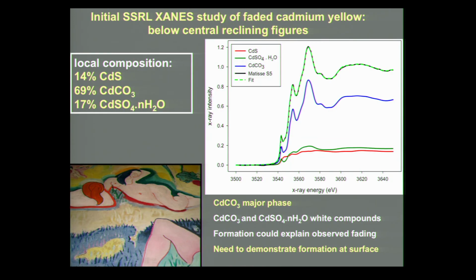So then we went on to study the faded paint under the central reclining figures here at SLAC, and what we found out was that the overall composition was less than 15% cadmium sulfide. So the cadmium sulfide has almost completely gone away under the central figures, and the paint is now largely made up of cadmium carbonate and cadmium sulfate. Well, cadmium carbonate and cadmium sulfate are both white, so that would certainly explain why the paint was fading. But again, we need to demonstrate that they're forming at the surface of the paint layer.